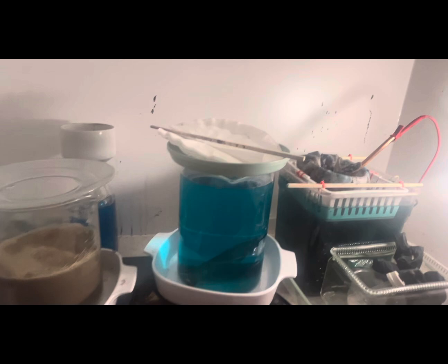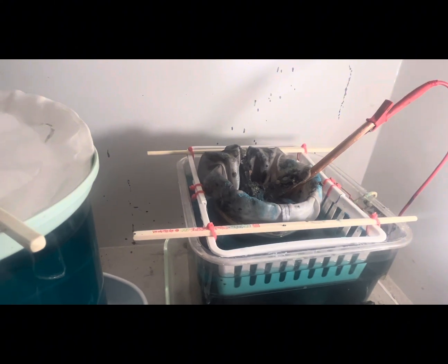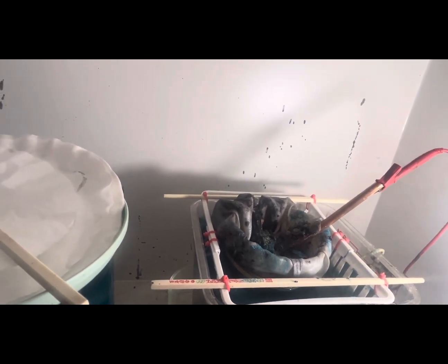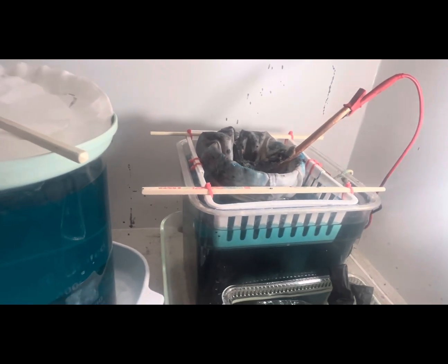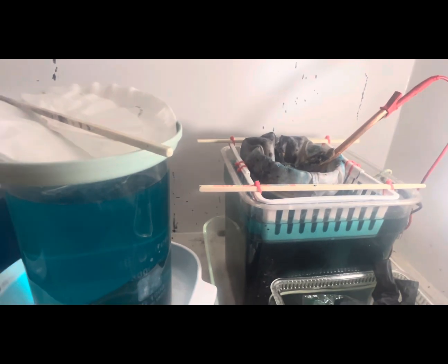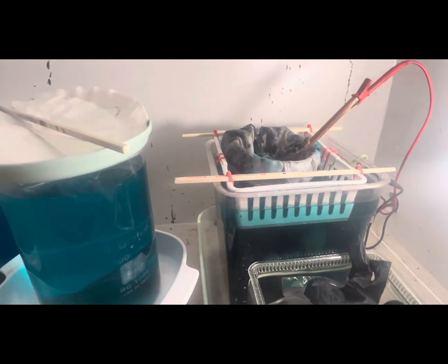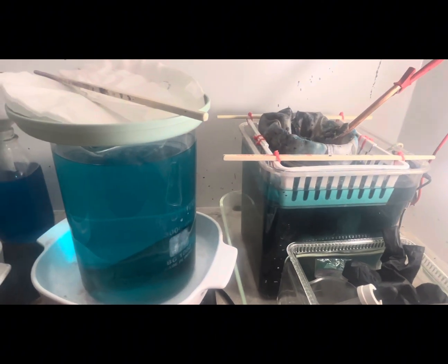This is what's left of the copper cell we're going after. I'm kind of getting tired of it — it's taking up a lot of room. If I increase the amps and the voltage it makes the copper on the cathode fluffy. I probably need to go back to the sheets we were using and get rid of the brain coral cathode. It's been fun but it's not really effective, so I need to pull that out and do something different.